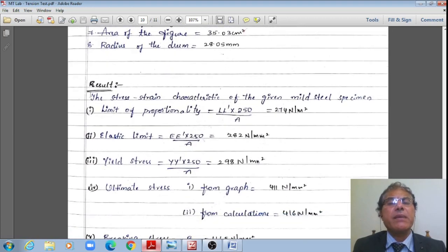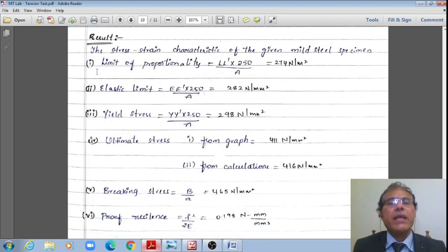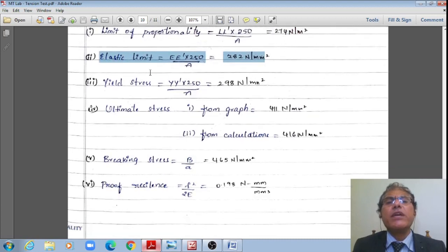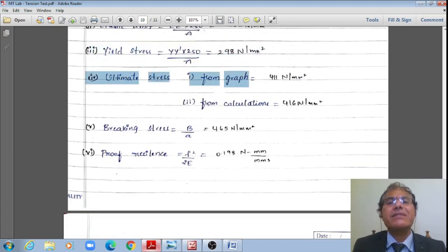Therefore, this data we already examined. Therefore, now I'll report finally the results, right? Therefore, these are the results. The stress strain characteristics of the given mild steel specimen. That first one, limit of proportionality is equal to 274 Newton per mm square, and elastic limit is equal to 282 Newton per mm square, and yield stress is equal to 298 Newton per mm square, and ultimate stress from the